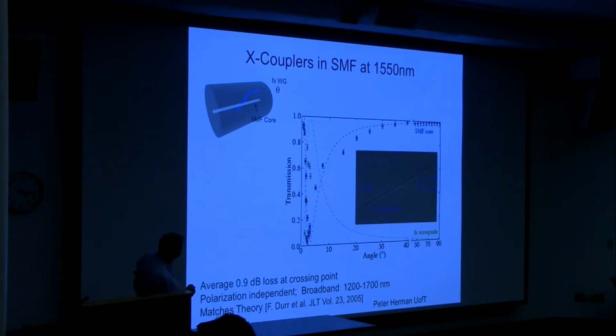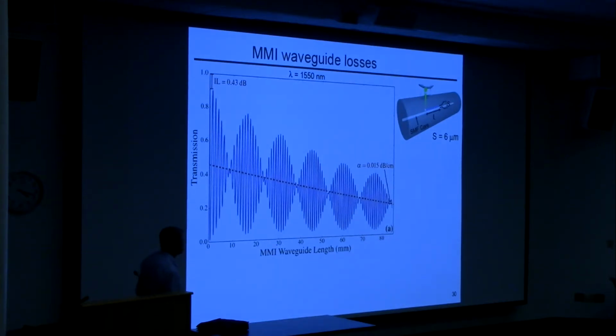And if you make a cross coupler, you vary the angle of this waveguide, and at 2 degrees, you see a huge drop in the power in the core waveguide. And if you measure the light that goes into the cross-coupled waveguide, we've gotten up to 78% or so light crossing over. So you can get appreciable amounts of light, and now think of making cool devices. Here is a kind of hybrid multimode interferometer directional coupler. If we stand parallel and close, in this case 6 microns from the center, here's the power that you see as a function of length or time, and you get this oscillation, which is exactly what a directional coupler does.